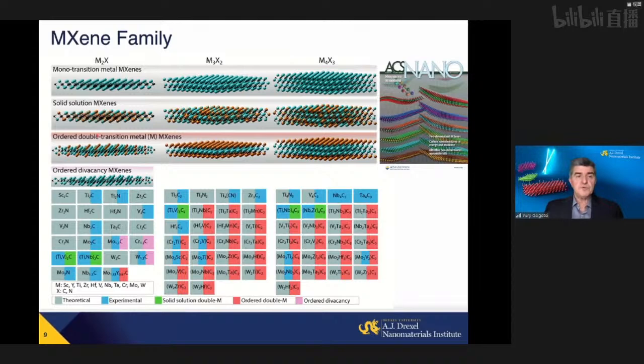It's also possible to make structures with alternating atomic columns of different transition metals, for example, molybdenum and yttrium or scandium. And if you remove yttrium or scandium, you end up with ordered divacancy MXenes, structures where monatomic columns of one element are missing. So you get the idea. We can really do atomistic engineering at the best level.